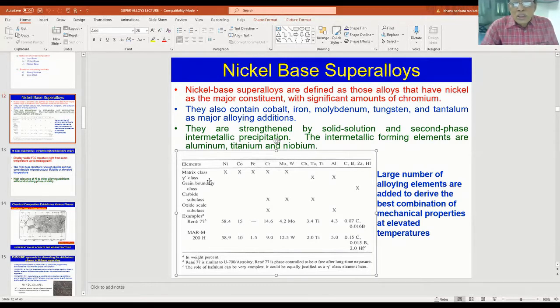This is the gamma prime class: titanium, aluminum, columbium, and tantalum. These are the elements which contribute to major strengthening of the alloy in the matrix. There is a grain boundary class. These are mainly those which form carbides on the grain boundary: chromium, molybdenum, tungsten, tantalum, titanium. You can see that titanium plays an important role as a gamma prime former, but at the same time, it also forms some amount of carbides generally.